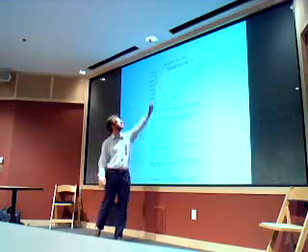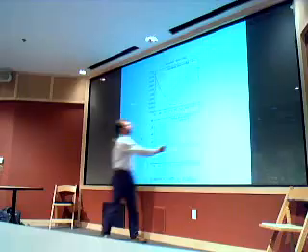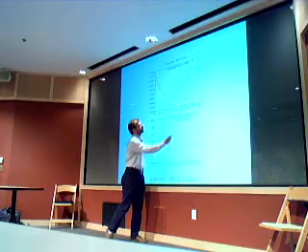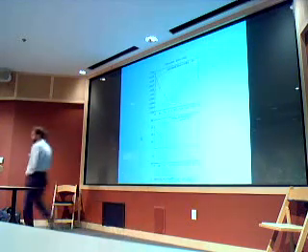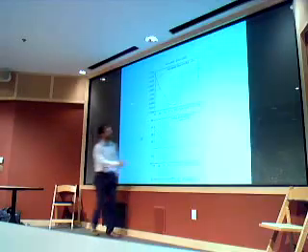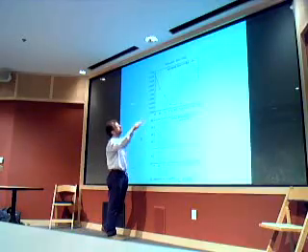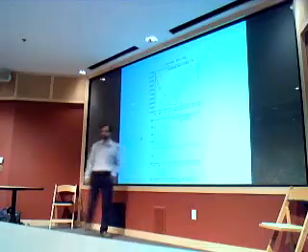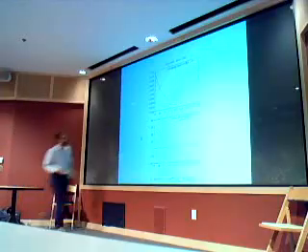If you calculate the total energy for several numbers of k-points at 16 Rydberg, then this is what you get. We are at 10.2, and so you would say that the minimum is somewhere between 10.2 and 10.3. If you calculate the stress, this thick line is what you get from the calculation, and the thin red line is what you get if you interpolate an equation of state through these points and then take the derivative of the equation of state.